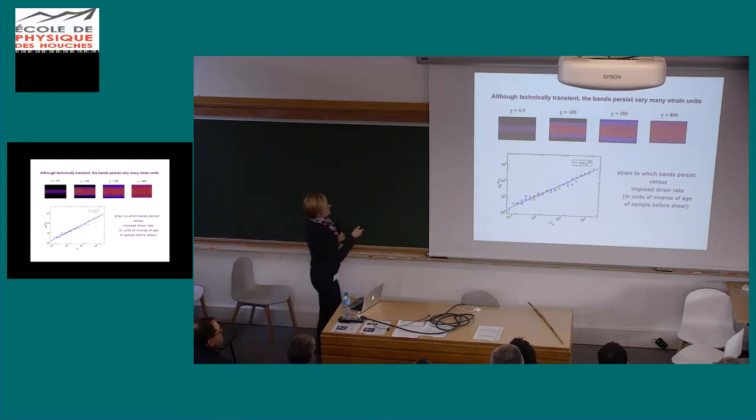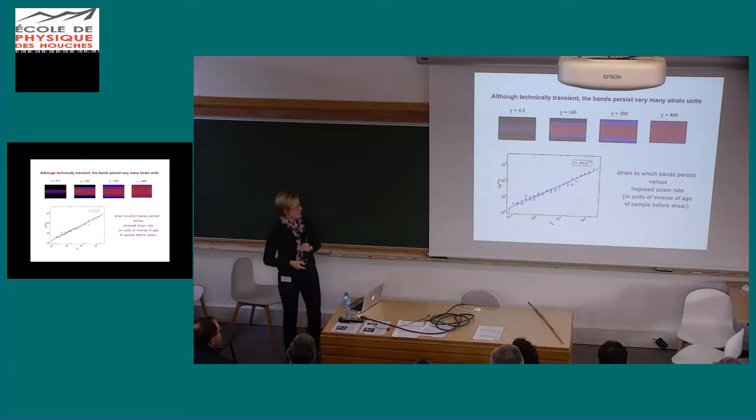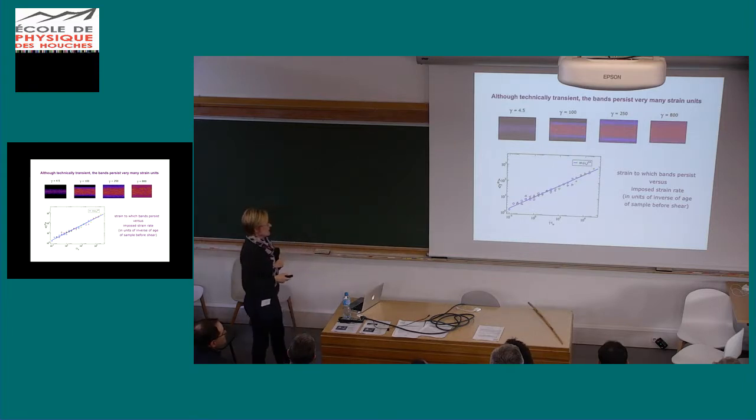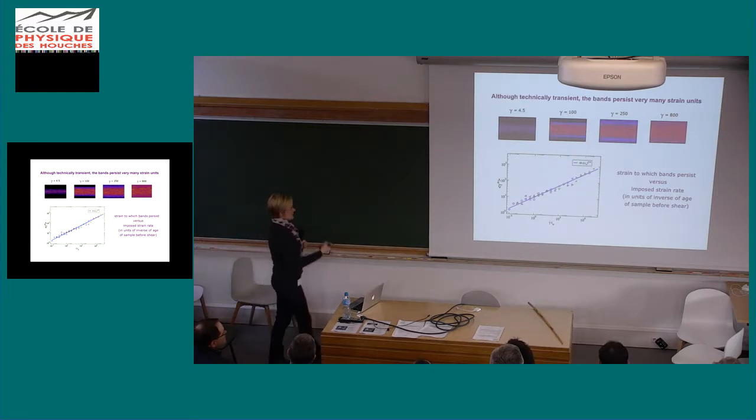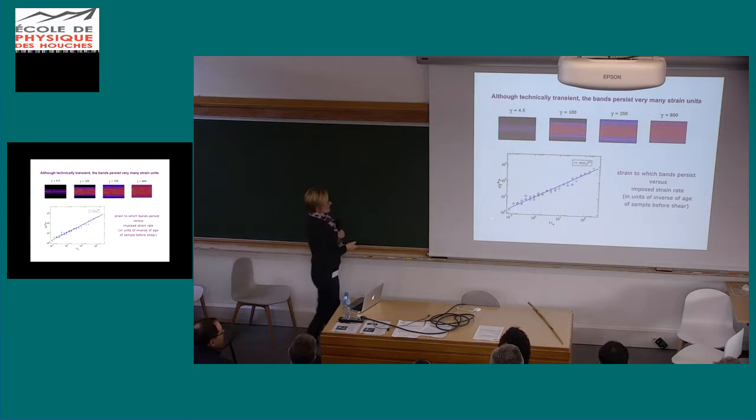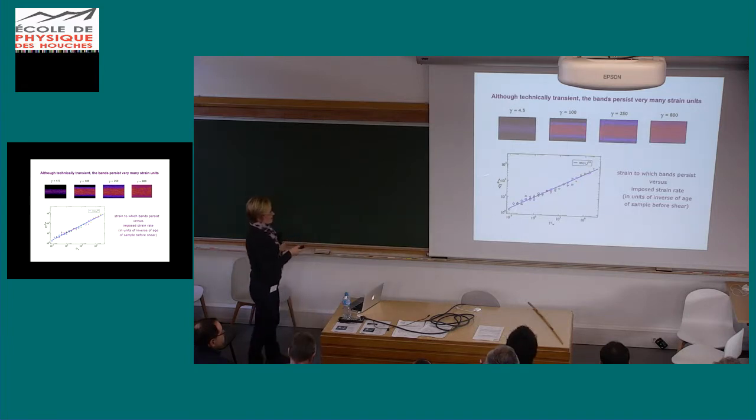And you see here a very pronounced shear band that then gradually coarsens away to leave a state of just homogeneous but nonetheless flickering avalanches in the ultimate homogeneous steady flowing state. Homogeneous in the statistical sense, even though there are still flickering avalanches. So I've characterized here this strain required to reach an eventual homogeneous flowing state.